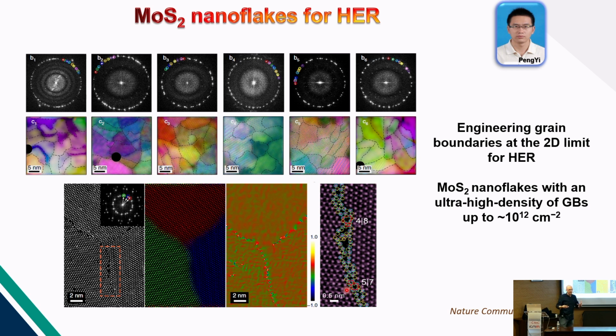It's not working, because the real catalysis would be done by the different molybdenums with dangling bonds. You need something to be attached to the, in this case, to the water molecules and destroy them and try to separate the hydrogen from the oxygen. But this is not possible with the basal plane of molybdenum disulfide.